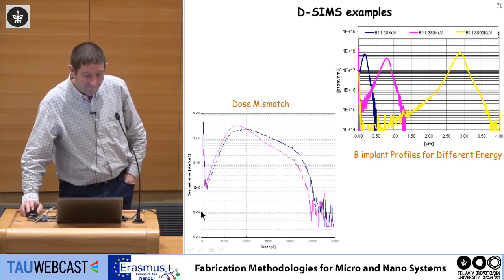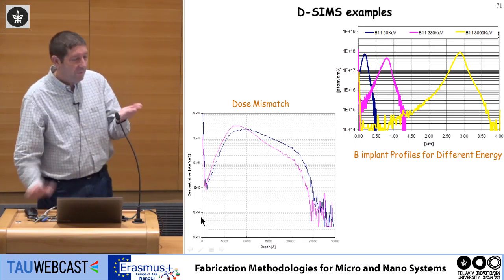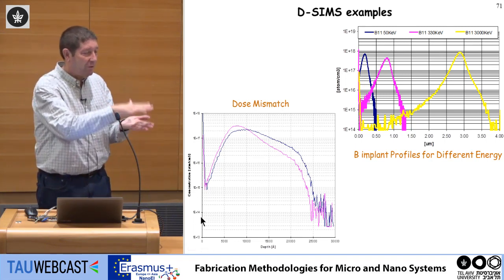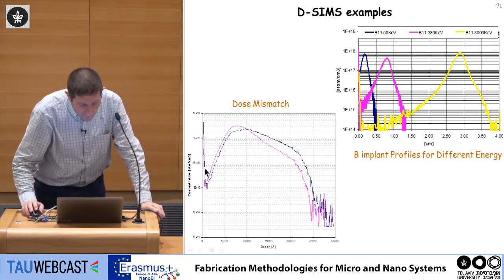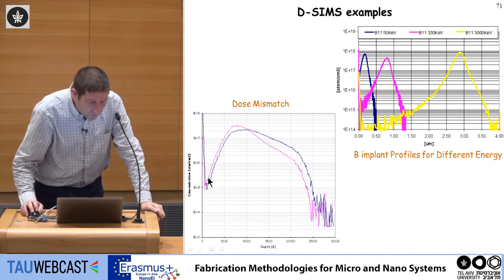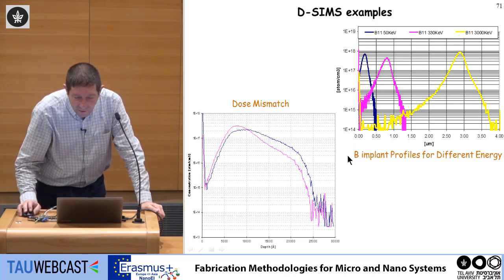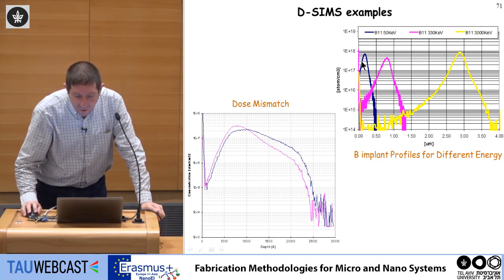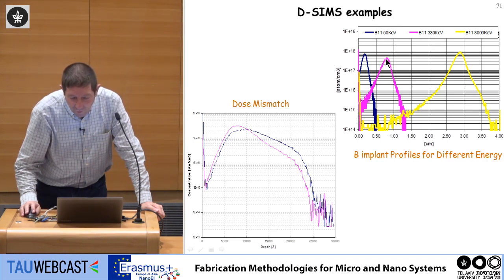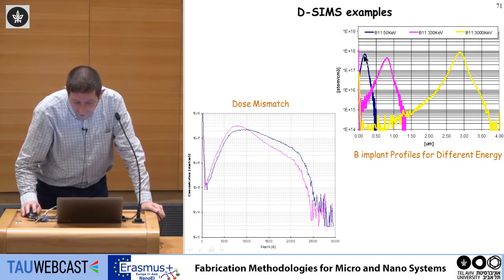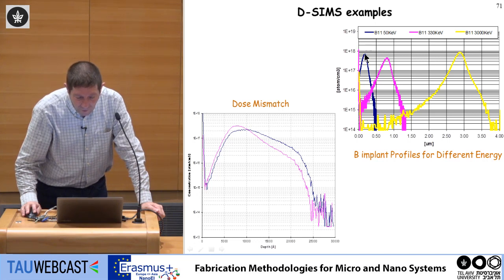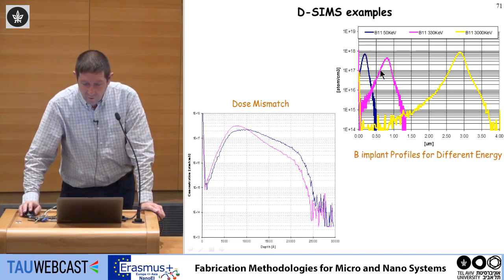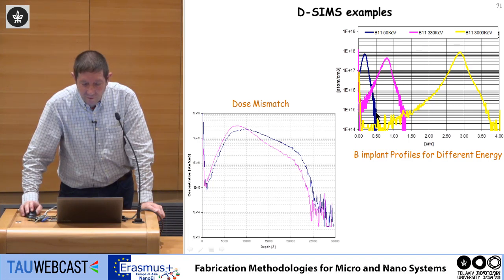What we do, we sputter and measure the composition. Sputter and measure, so we can build a profile. For this example, it's doping or material concentration versus distance. This is a boron implant for different energies. This is boron 11 50 kiloelectron volts, 330, and 3000 kiloelectron volts. This is the profile of implantation into silicon. It doesn't say if it's silicon. Probably, we don't see channeling here, so it's probably an angled implant.